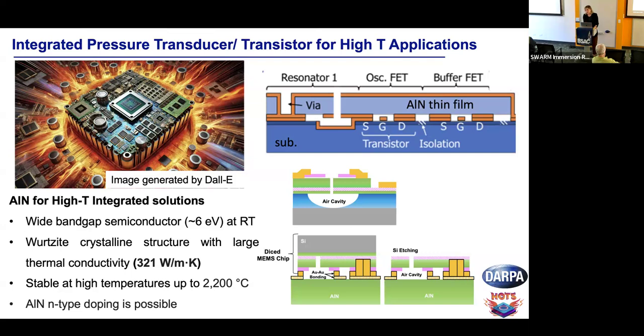So I was curious when you choose bonding the integration. That's a great question. So we're using platinum for now, and platinum is pretty stable at high temperatures, and we're using metal bonding. There are other things that you can use. For example, you can use ALD zinc oxide and anneal it, to make sure that at high temperatures the bonding is stable. But for now, platinum is what we have been using.